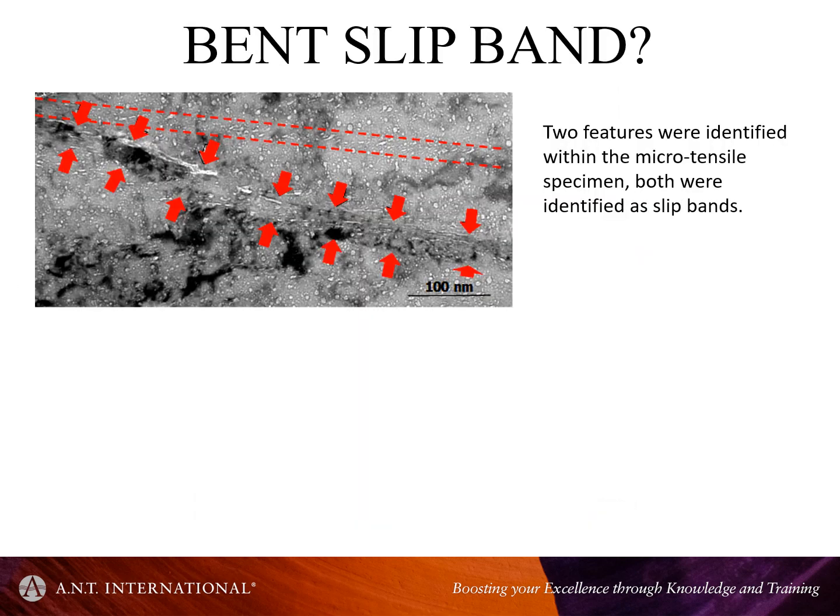One other feature of the work that you have to dig into the micrographs a little bit more to see is that this feature ran right the way through the material, across the grain, and you could see where there was a high propensity for cracking in this microtensile test. And again, they related this to shearing of the cavities creating cracks somehow, and even described this edge component as the shearing of the cavities from dislocation slip. And again, it doesn't make any sense because a slip band has an edge to it, but that's an artifact of how the sample was prepared.